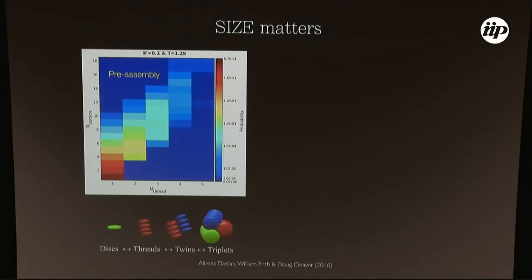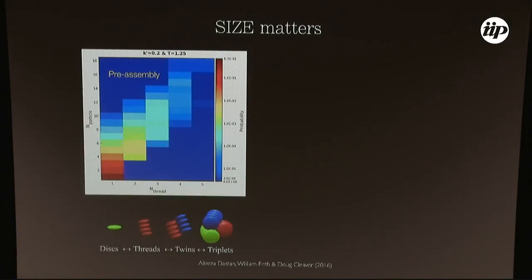When two of these stacks come together, they're going to interdigitate, and there's again no chirality. There's just a symmetry between them. But when you've got 3, then it wants to interdigitate with both the first bundle and the second bundle, and it can't do that because there's a shift in registry. So what happens is everything reorients and tilts over, so you can have these chiral structures like this. You need this structure in order for the whole bundle to grow. Before that, everything will assemble and fall apart and assemble and fall apart, and you need a seed like this to form in order for the entire system to grow.